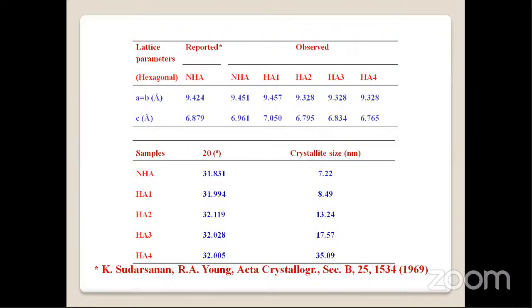No. Crystallite size is very, very small when compared to the particle size. Crystallite size is entirely different from particle size. If you take one particle and look at its structure, one could find a large number of grain boundaries. Each and every grain will have a collection of crystallites, that is, internal domains. When you increase the temperature, the domain will grow. Can you imagine? Let us consider your particle in a spherical shape.